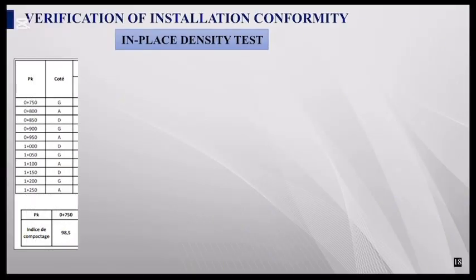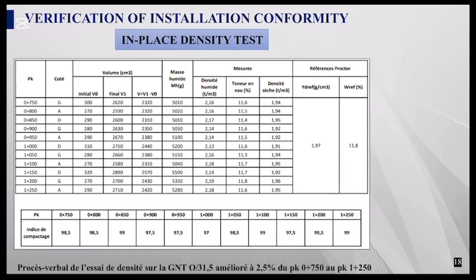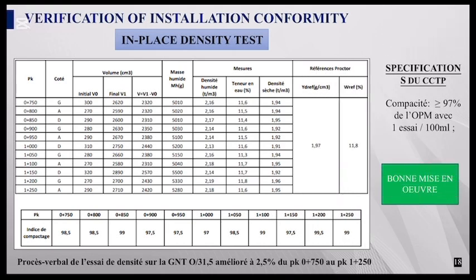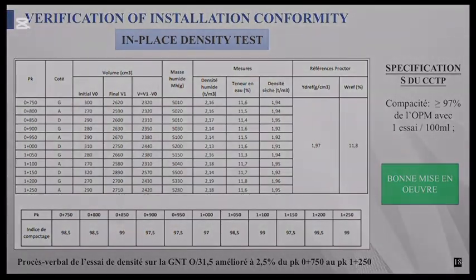After laying the GNT base course, the company carried out a verification test in the presence of the inspection team. The density test is an in-situ test to determine the dry density of the layer in order to assess its degree of compaction. The CCTP requirement for the in-situ density test is a compactness greater than 97% of the OPM. In our case, we have 100% of values above the 97% of OPM. This is therefore a good implementation.